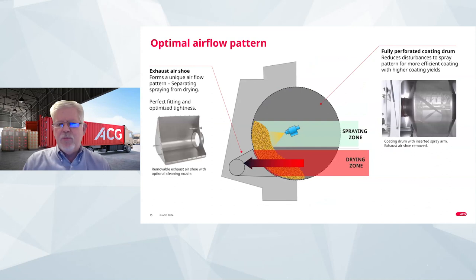The first is ensuring an optimal flow pattern, both in the spray and in the airflow or the drying capacity that's brought into the system. Now, one of the unique aspects of the ACG design is actually a separation of the spray zone from the drying zone. Now, the tablet bed itself, which is positioned in the lower left quadrant of the drum as the drum is rotated in a clockwise direction, we utilize the upper portion of the bed for your spray zone. And then we use the lower portion of the bed for our drying air.